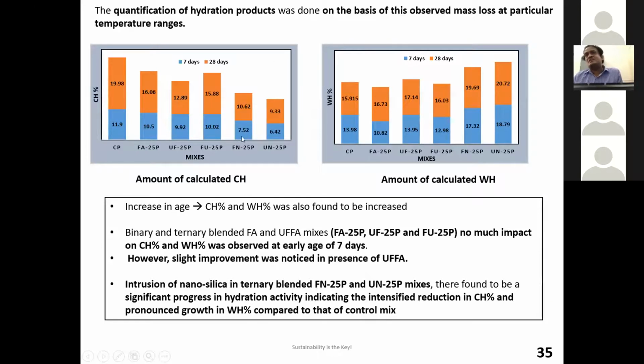So what are we understanding? Well, we are understanding that the moment I go towards binary, as compared to control, your CH is getting reduced. Same thing for your 28 days also. Now, when I'm going with the multi-blended, ternary blended, or I'm having nanoparticles, I'm drastically reducing the capillary porosity. So you can see here at 28 days, it is almost 20%, but here it is less than 10%. So that is the way I'm going to increase the durability of my material.